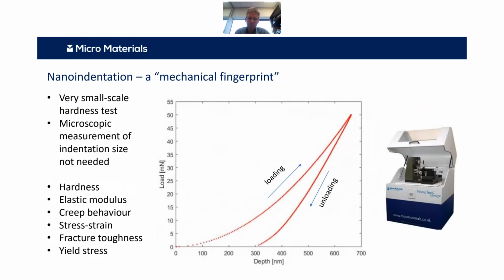So for those that don't know, nano indentation is essentially a very small scale hardness test. We're applying a load, or a force, to a very sharp point, and then we're indenting into a material, and there's some penetration, and then as we unload, there's some partial recovery, and contact mechanics is applied to that unloading slope to determine primarily the hardness and elastic modulus, but there's also a range of other information you can get from these type of tests.